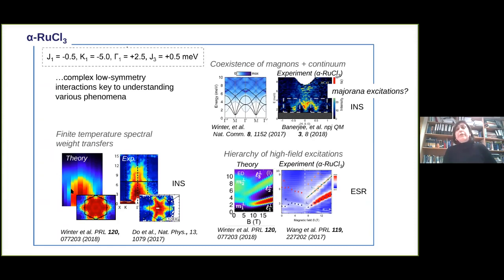The same is for observations, for instance, of shifting of finite temperature spectral weight, that it's a consequence of these anisotropic interactions, and this can also be described by such a model, for instance, here by using finite temperature Lanczos measurements. And a third important feature of this material is its behavior on the magnetic field, where there is a hierarchy of high field excitations that are also a consequence of these anisotropic terms.